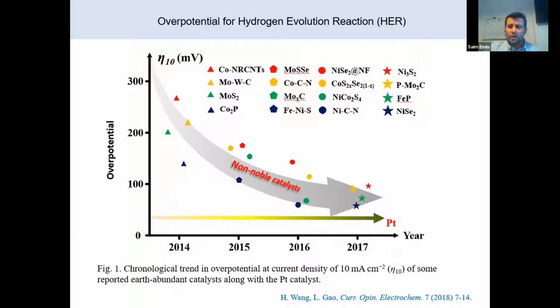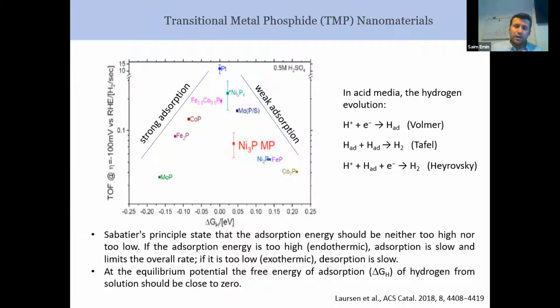Nowadays, different classes of catalysts are developed and studied that can evolve hydrogen close to platinum. These are metal phosphides, metal selenides, metal sulfides, metal carbides, transition metal carbides. This makes this class of materials quite attractive, because platinum is very expensive. And why is platinum good initially? Because the adsorption of hydrogen on the platinum surface and the desorption are very balanced. It's close to zero here. That means this is one of the good systems for hydrogen evolution.